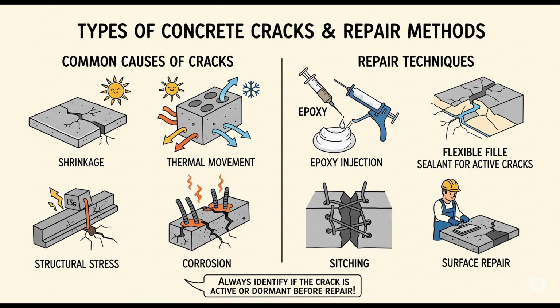Wow. And then you mentioned steel. Yes, and this is one of the most critical ones, corrosion of reinforcement steel cracks. This is when rust forms around the rebar, the steel bars inside the concrete. Rust is expansive, it takes up more volume than the original steel. This expansion puts immense pressure on the surrounding concrete, which leads to longitudinal cracks appearing along the rebar's length. Eventually, this can cause the concrete cover to spall off, basically pop off, leaving the rebar exposed.